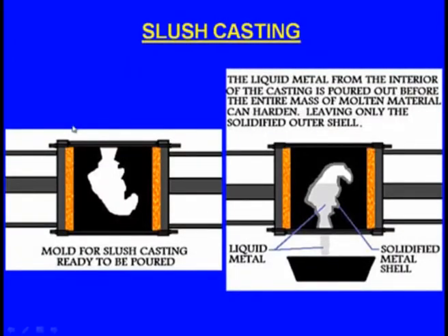In the slush casting process, a mold cavity is already created and ready for pouring. The liquid metal is poured from the interior of the casting, and before it solidifies completely, the mold box is turned upside down. Solidification starts from the mold wall and slowly increases. Once solidification reaches a thickness of a few millimeters, the inside still has molten metal. Making the molding box upside down allows the still-molten metal inside to drain out.